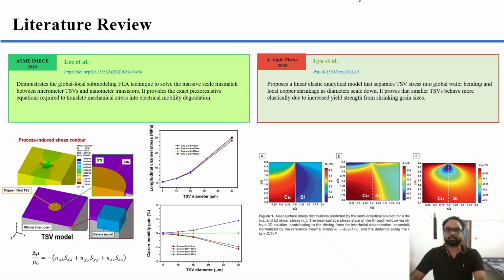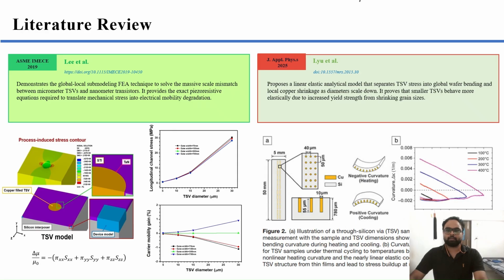The key message is that near the surface of silicon, the stress pattern is far more complex and dangerous than what simple 2D calculations predict, and this is what can cause the copper-silicon interface to crack and peel apart. So in the next figure, we can see an actual TSV test sample, a piece of silicon with copper wires arranged in a grid about 40 micrometers wide and 50 micrometers apart. On the right, you can see what happened when you heat it up. The wafer went upward, curving negatively. When it's cooled back, it bent the other way, that is positive curvature. The graph shows its behavior measured at 4 different peak temperatures.